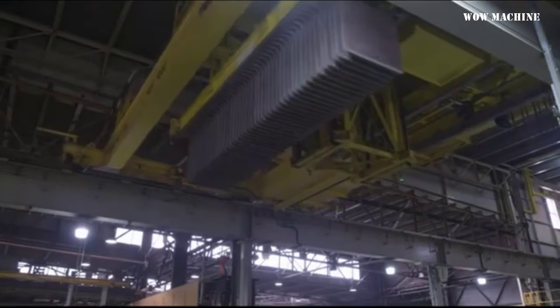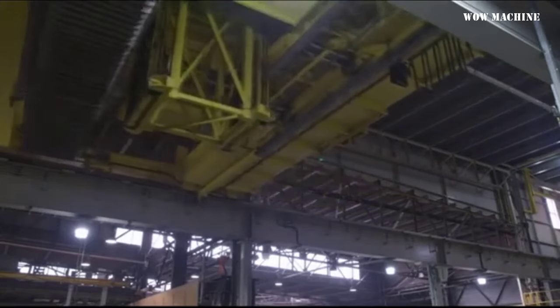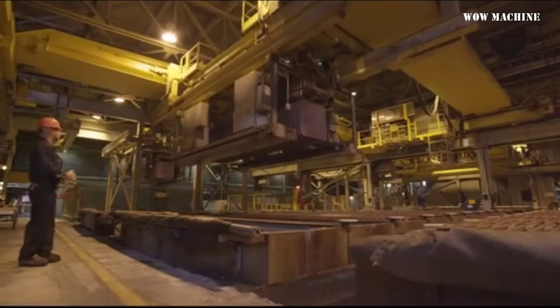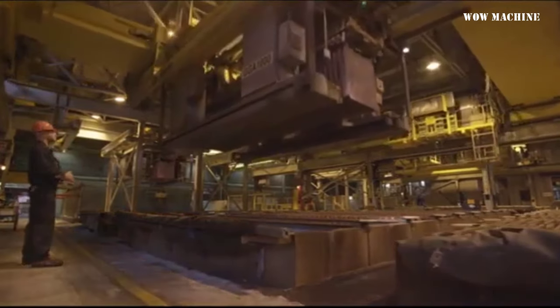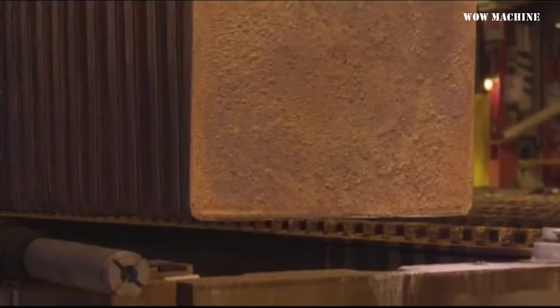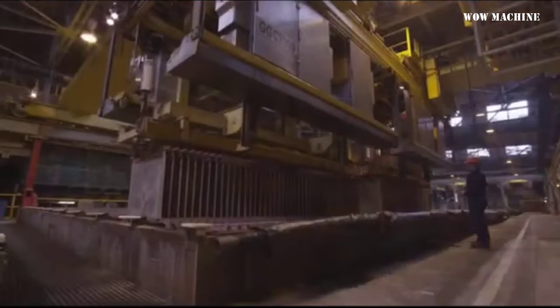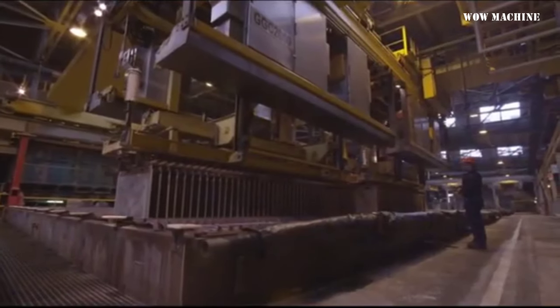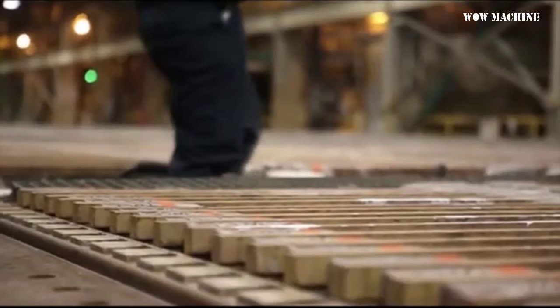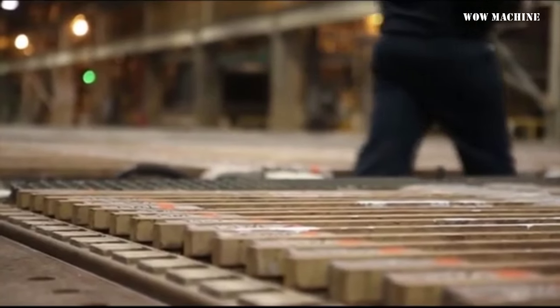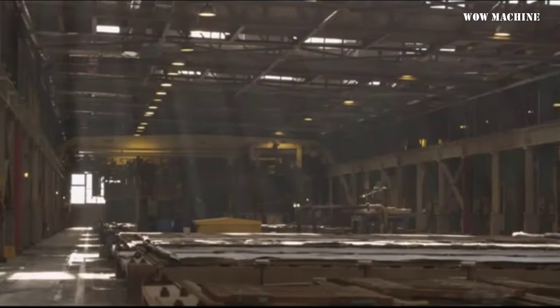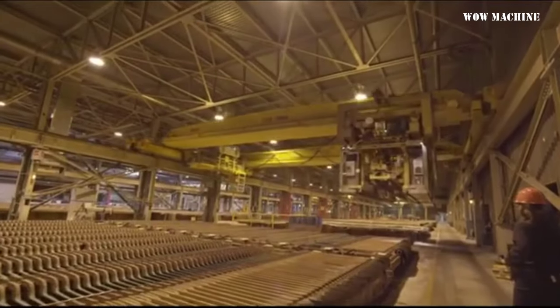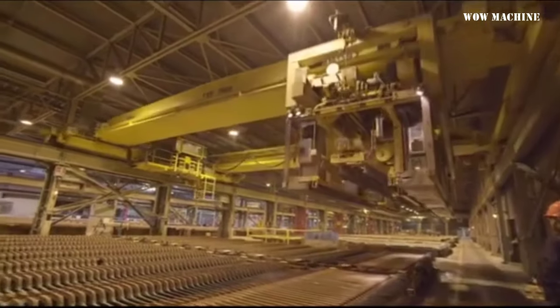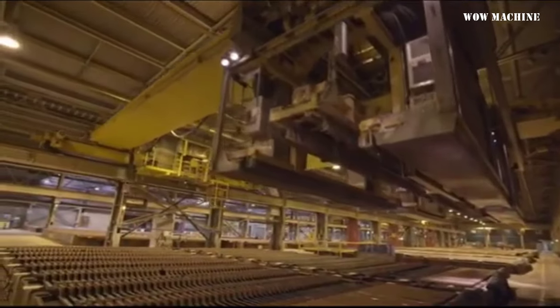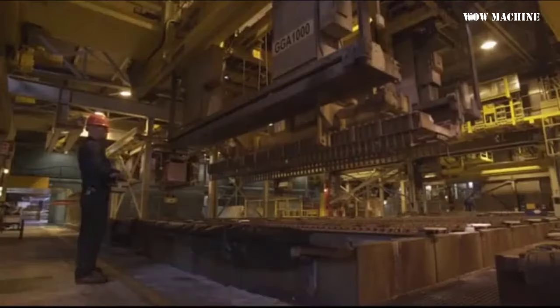The refining process begins with the arrival of copper in the form of anodes, large plates weighing 340 kg each. After weighing, sampling, and initial treatment, these crude copper plates are placed into tanks of electrolyte, a mixture of sulfuric acid and dissolved copper. Stainless steel sheets, known as mother blanks, are positioned between each anode in the tanks. An electric current is then applied to initiate the electro-refining process, where pure copper dissolves from the anode and deposits onto the mother blank, forming a new copper plate with maximum purity, known as a cathode.